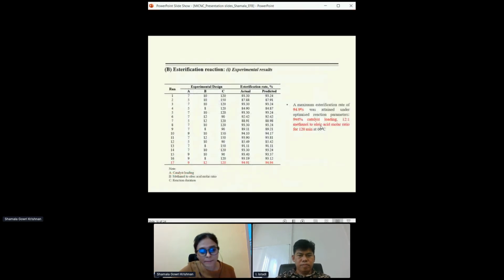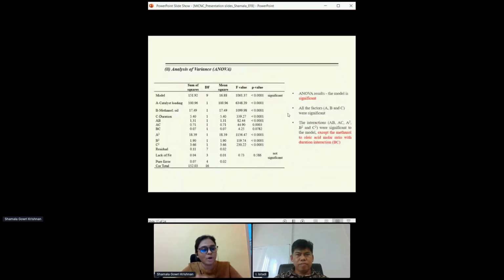Moving on to part B of results and discussion, a set of 17 experiments were generated, and the experiments were conducted based on the arrangement. It was observed that a maximum esterification rate of 94.9% was obtained at the optimized reaction condition of 9 weight% catalyst loading, 12 to 1 methanol to oleic acid molar ratio for 2 hours of reaction at the fixed reaction temperature of 60 degrees Celsius.